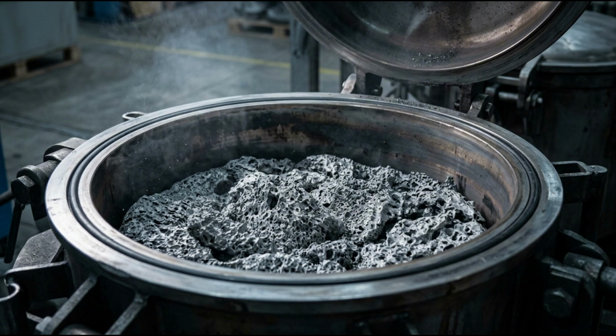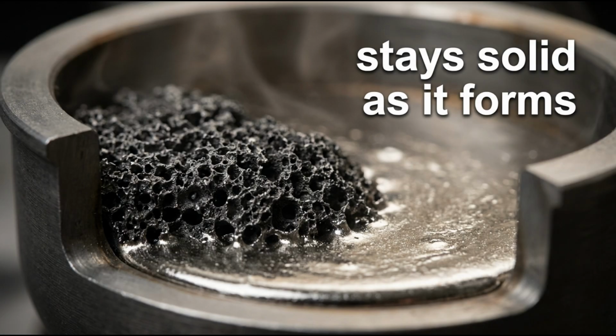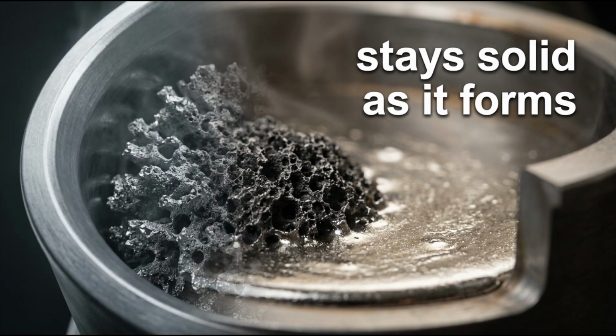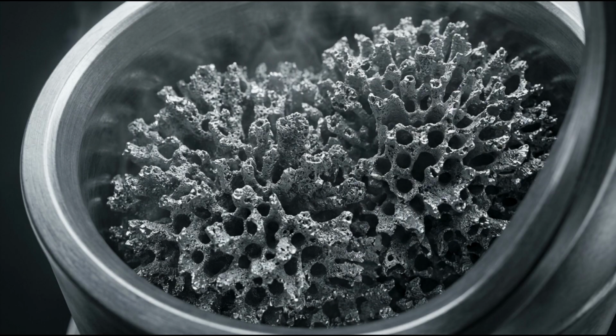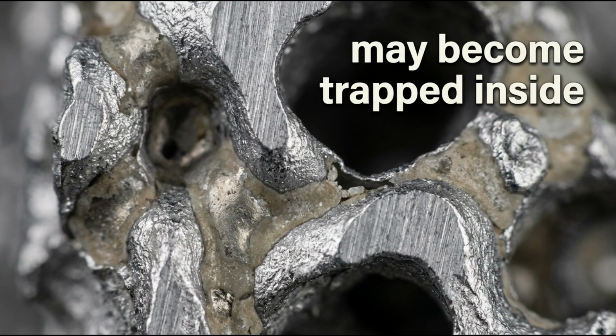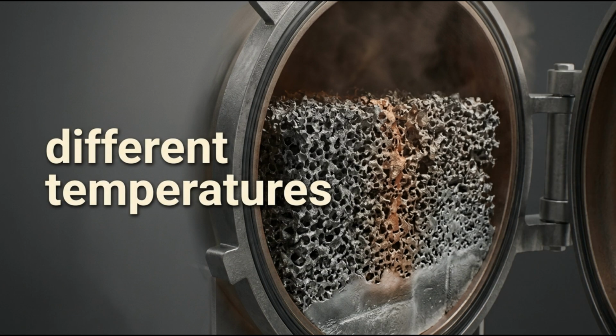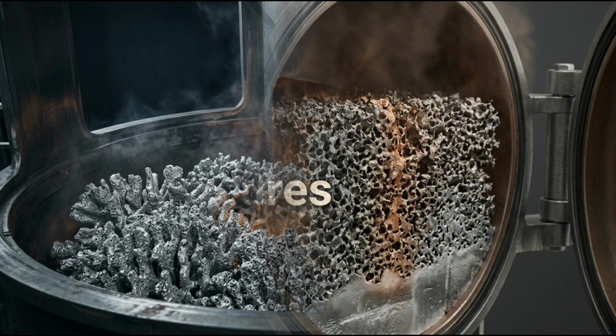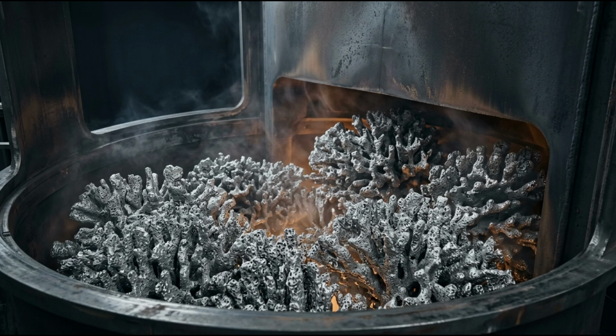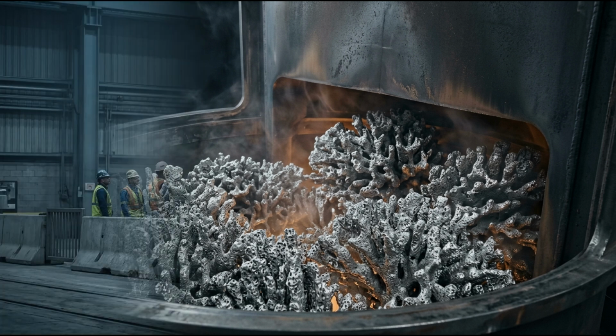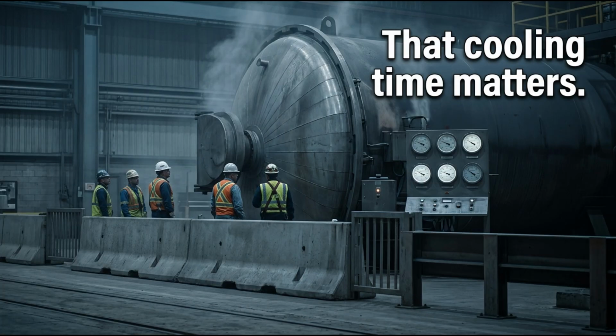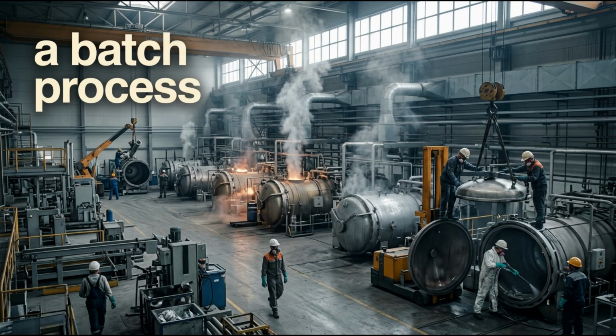The reaction temperature is far below titanium's melting point, so the new titanium stays solid as it forms. It grows into an irregular porous mass inside the vessel. Magnesium chloride fills the spaces around it. Excess magnesium may become trapped inside. Different parts of the growing mass may experience different temperatures and different contact with the reacting materials. The reactor gradually fills with something that looks less like an ingot and more like metallic coral. When the reaction ends, the vessel must cool before it can be opened. That cooling time matters. The Kroll process is a batch process.